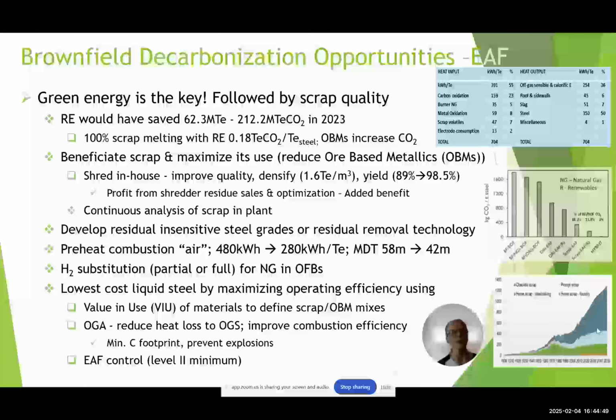For the EAF, green energy is the key, followed by scrap quality. Renewable energy would have saved 212 million tons of CO2 in 2023 if it had been available. 100% scrap melting, as you can see on the right-hand side here, will give us 0.18 tons of CO2. If we beneficiate scrap, maximize its use, and avoid using the DRI, HBIs of the world ore based metallics, then we're going to have a much lower CO2 count.